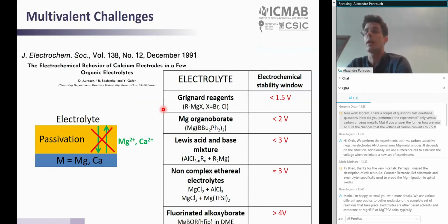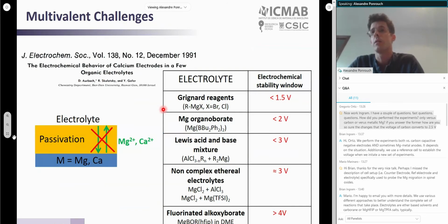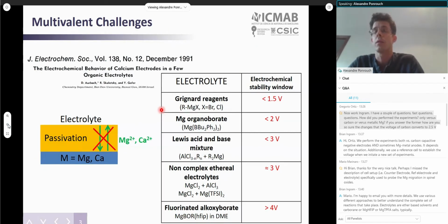In the early 90s, the group of Professor Aurbach pioneered this divalent cation chemistry, mentioning that those metal anodes are strongly surface film controlled. So as soon as you get some kind of passivation layer, it tends to block the electrochemistry, blocking the divalent cation migration through this passivation layer.